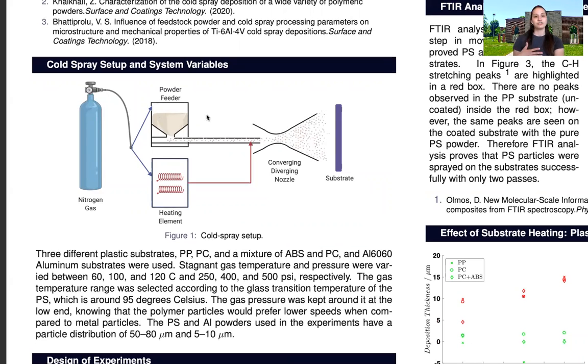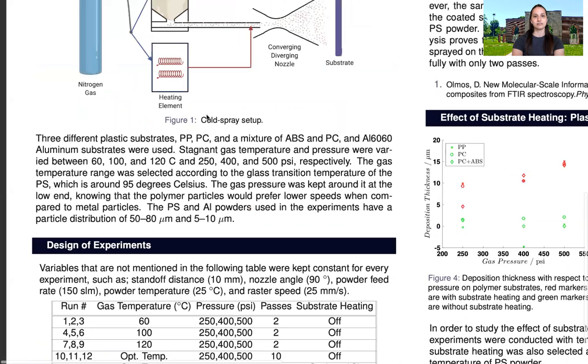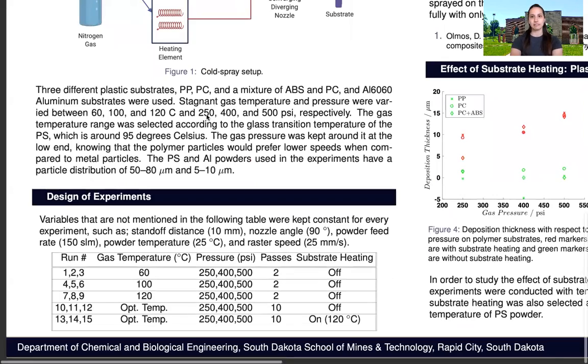We kept the gas pressure in the lower spectrum, between 250 and 500 psi, knowing that the polymer particles would prefer lower speeds when compared to metal particles. And this is our design of experiment table.